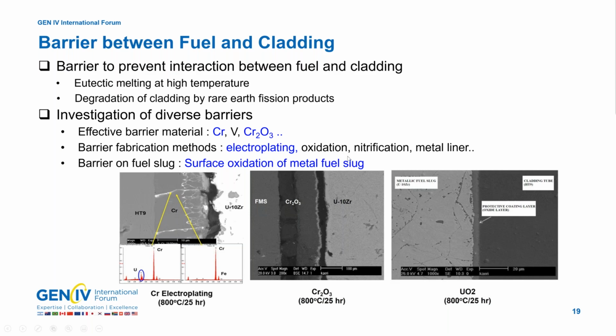And we also did studies on other electroplating and liner options. And also we studied not only the cladding inner surface but also the surface oxidation of the fuel slug itself. It's easy to form because the uranium fuel slug surface is easy to oxidize, so we can form a very thin oxide layer here. And we tested the chemical interaction between cladding and fuel slug, and it works well. So based on these results and for practical reasons, we chose the electroplating of chromium as the main barrier candidate.